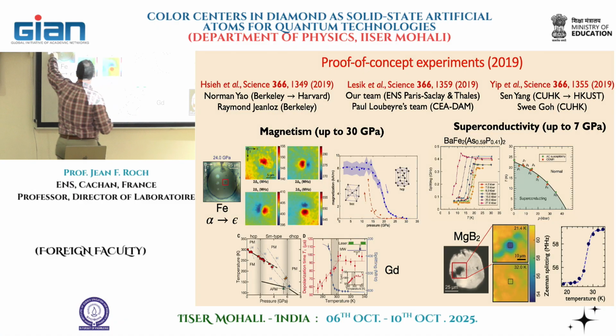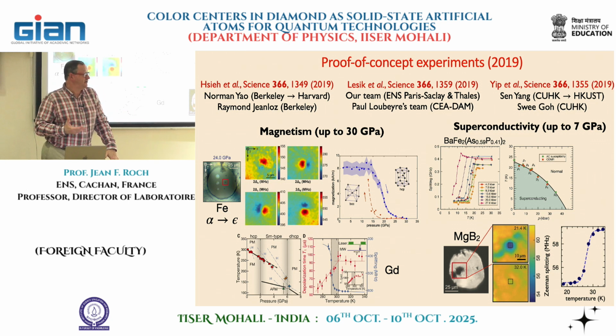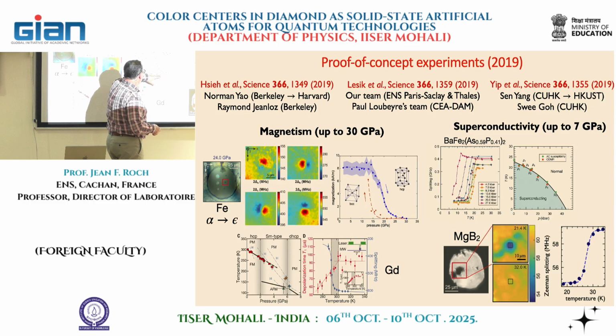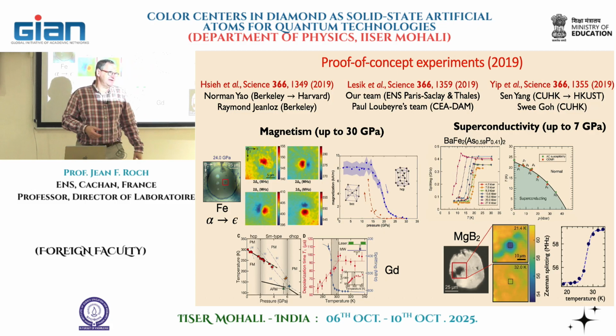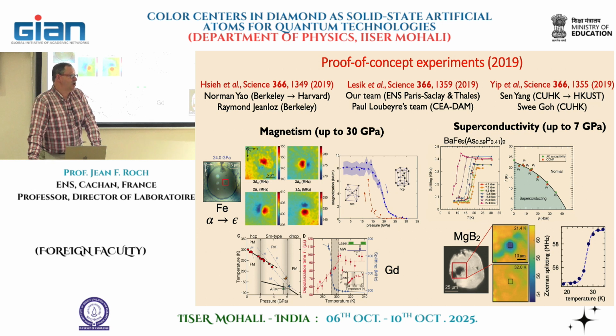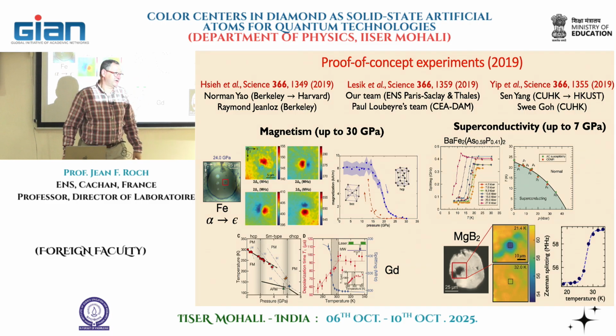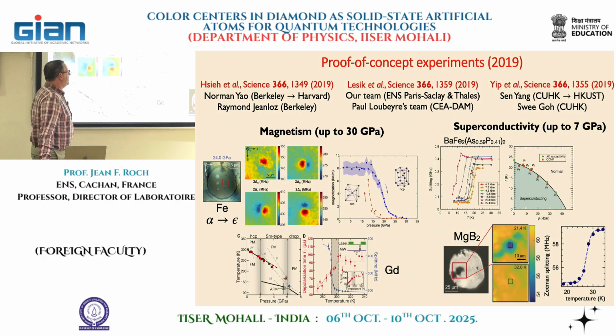So what we do is we have here inside the sample little beads of iron, and we apply pressure on them. From the bead of iron, we magnetize them with this technique. And again, with our 4 NV orientations, we can really directly see the magnetic field arising from the bead. We can even go to a really quantitative measurement by, again, the same approach as I showed you with the permalloy dot. And when we increase now the pressure, the magnetic field produced by the bead will get smaller, smaller, smaller, and smaller until it disappears. And if we release the pressure, we see that the magnetic response starts again. There is some hysteresis due to the size of the bead and the fact that it's certainly non-monocrystalline, not a single crystal, but we could see that until at one point we do not have points afterwards because we broke the anvil. That sometimes happens.